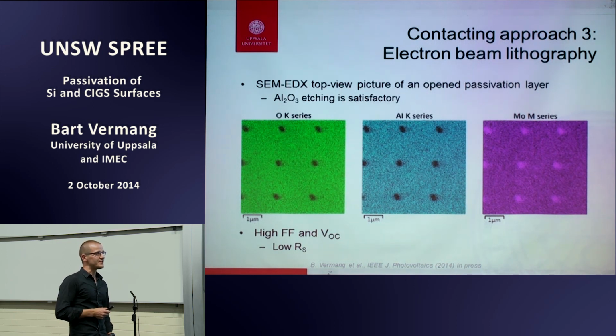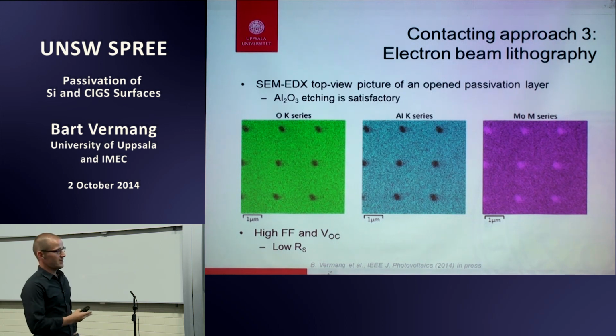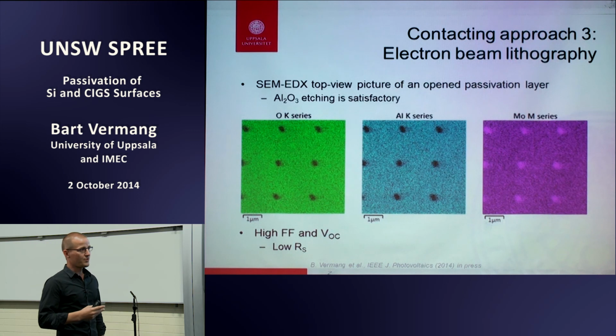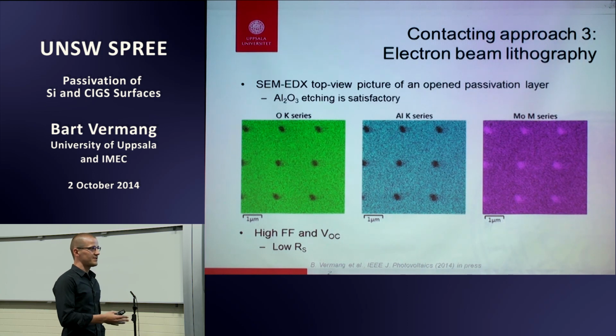It's the aluminum oxide. I'm thinking about it. I have a few reasons in mind, but I have to choose a good one. Oh yeah, the blistering maybe. Even for thin layers, we have seen the same effect of blistering of the aluminum oxide after depositing the CIGS layer on top of a full layer. It seems the sodium tries to get into the CIGS layer, but it didn't really work. And we got also a lot of blisters and this kind of things.